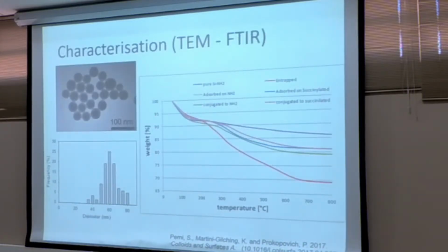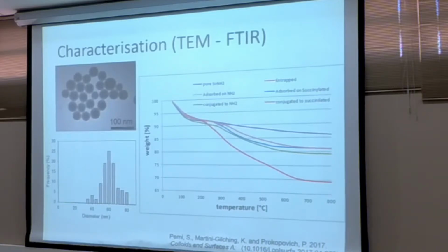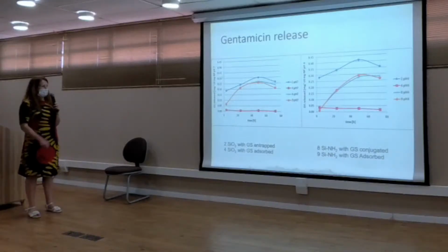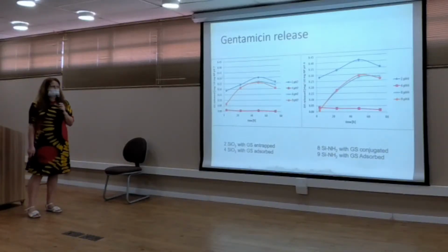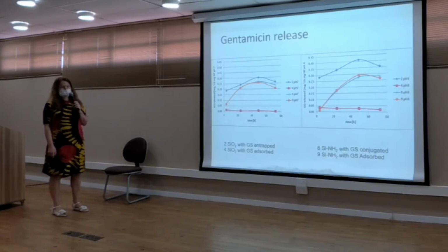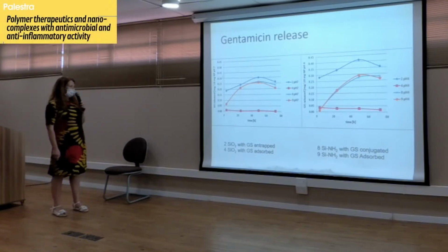So once we prepared all these different formulations, all these different nanoparticles, we looked at the size, shape, composition, and the ratios between organic and inorganic matter, just to ensure that we do not have variability from batch to batch in our nanoparticle preparation. And finally, for the functional experiment, we did release of gentamicin into PBS media from our nanoparticles.